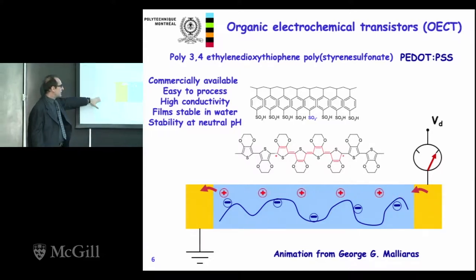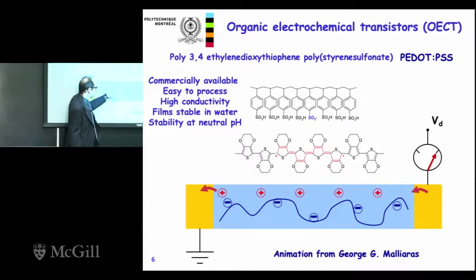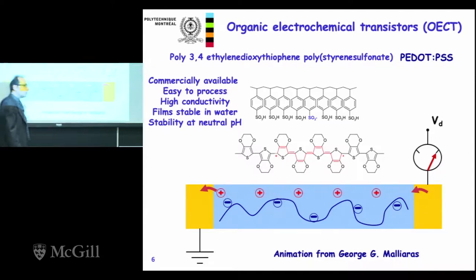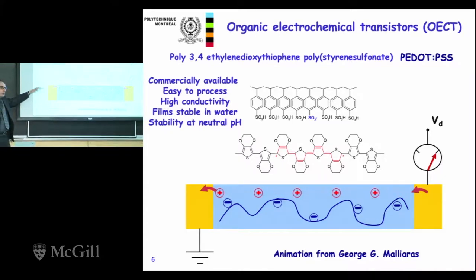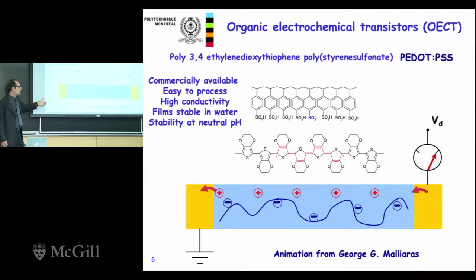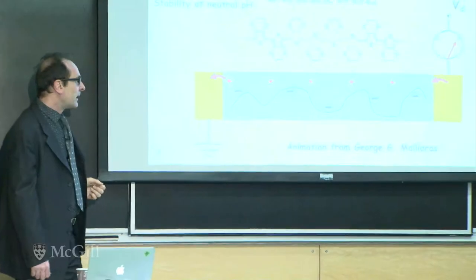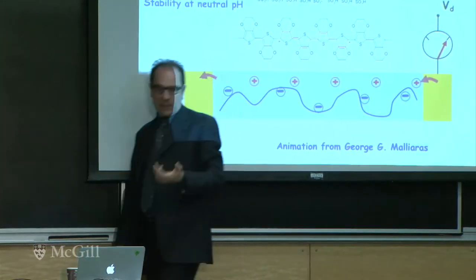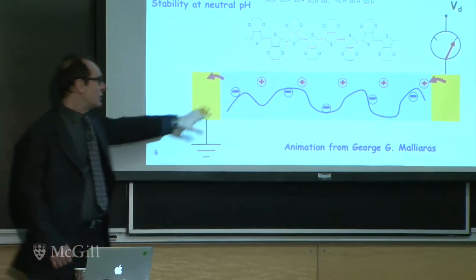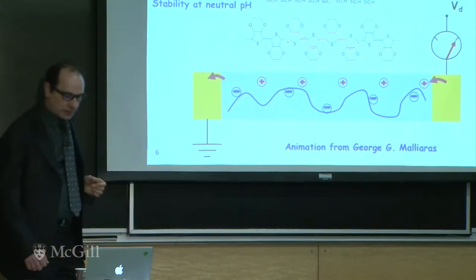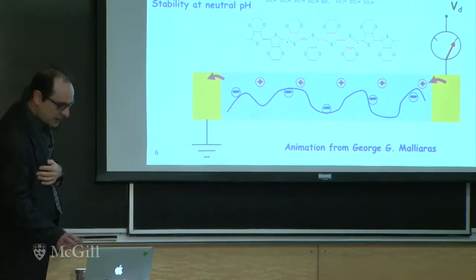Here you see an example of a film of this material between two metal electrodes, and this is what happens if you apply a voltage. You have electron holes flowing from one electrode to the other, depending on the polarity you apply. And these minus signs here are the dopant negative ions. Because of the presence of these dopants, you can have this high conductivity. This is just a simple two-electrode system.